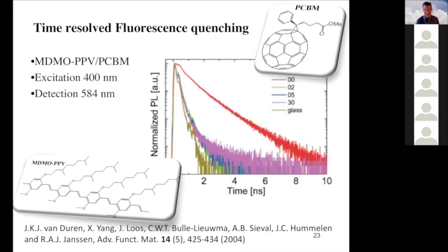Now we can also look at the time-resolved emission. The emission is monitored from the polymer, and you see that at 0%, the red line here, this is the emission of the polymer by itself. So it is on a nanosecond time scale. You see it is a normal fluorescent signal with a lifetime of a couple of nanoseconds. This scale here is logarithmic, so a linear line on the logarithmic scale means it's an exponential decay. We will come back to that to remind you.